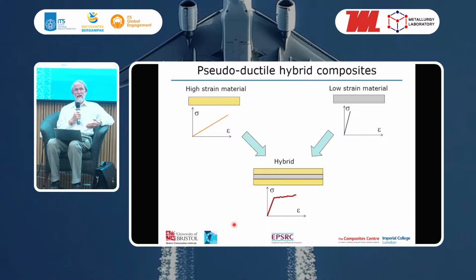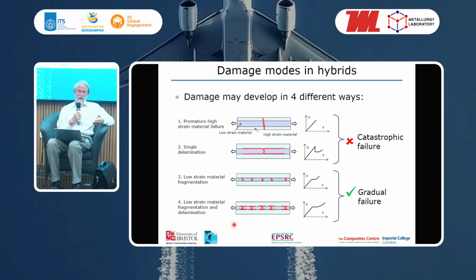So in order to understand that, we have to understand what are the damage modes and how damage may develop in a hybrid composite. So there are at least 4 different ways. If we start off with this first one, if we have too much carbon versus the glass, then when the carbon fails, the load at that point is immediately transferred to the glass, and there's not enough glass to carry the load. The glass immediately fails, and so you get a brittle failure at this point here. So it's not pseudoductile.